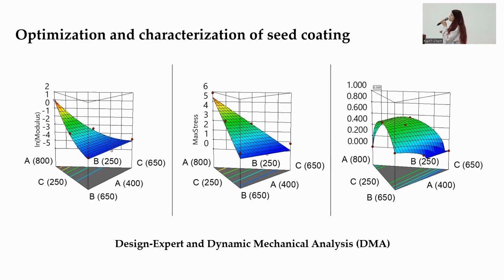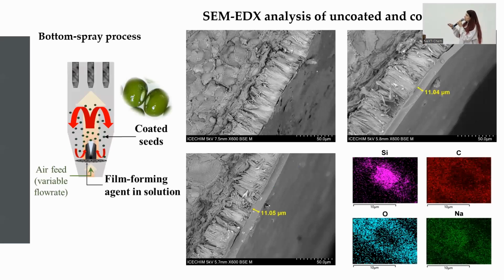Then we optimized a seed coating using Design-Expert software and dynamic mechanical analysis, and based on traction tests, we obtained Young's modulus and ultimate tensile strength. For the optimum seed coating, we minimized Young's modulus and maximized ultimate tensile strength in order to obtain the most elastic film, but one which also has a higher ultimate tensile strength to be good for seed-to-seed impact, because the seed coating was achieved by a bottom spray process.